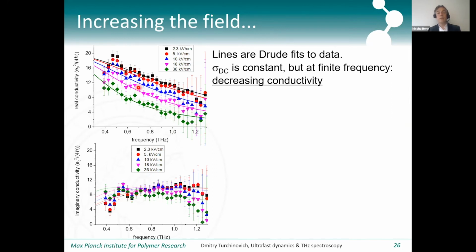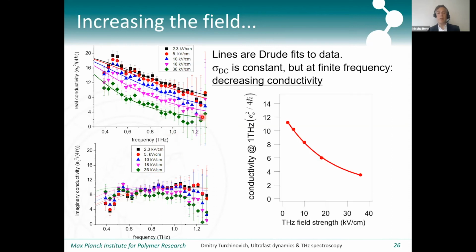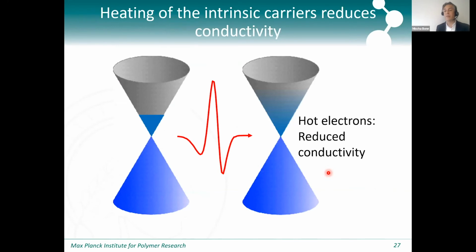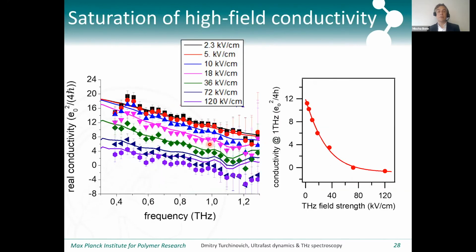So the interesting thing is that we can still describe all these traces using the Drude model. And here you see the drop of the conductivity. This is now at 1 terahertz as a function of field strength. So you see that already at the lowest field strengths, there is a dependence. And that is the same thing that we observed, this is how we interpret it at least, in the optical excitation experiment. So it's simply that we're heating the electrons with our terahertz pulse. Those hot electrons have a reduced conductivity, and that is what we're seeing here.